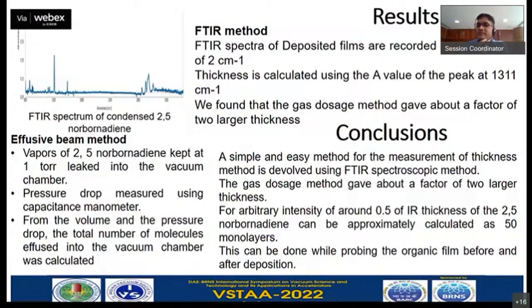If I understand you correctly, is this method of calculating the thickness independent of the FTIR? The FTIR is a separate thing? Yes. First we are using FTIR, but we calibrated using the effusive beam method. So now we have the probing method for FTIR, so we can directly calculate the thickness from the IR intensity. So how far was your method in agreement with this FTIR? It is twofold. We have found that the gas dosage method gave about a factor of 2 larger.